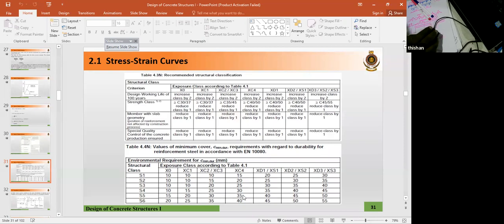So if the beam is in situ cast, we need 35 millimeter, but not only 35 millimeter, anything in situ cast, then this code says have a construction tolerance of 10 millimeter. So the beams will need 35 plus 10, 45 millimeter cover. Because the slab is precast, we can go with 30 millimeter cover. And because there can be minor variations I would go for something like 35 millimeter cover for the slabs and about 40 millimeter cover for the beams. We just add a little more so that, you know,